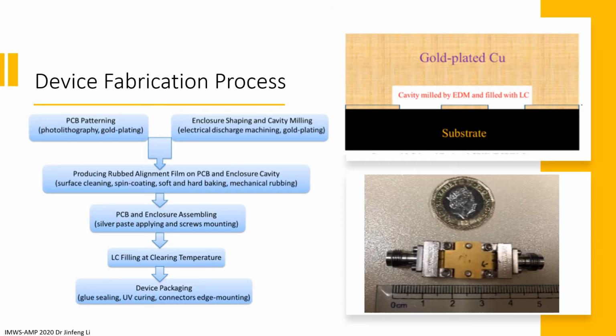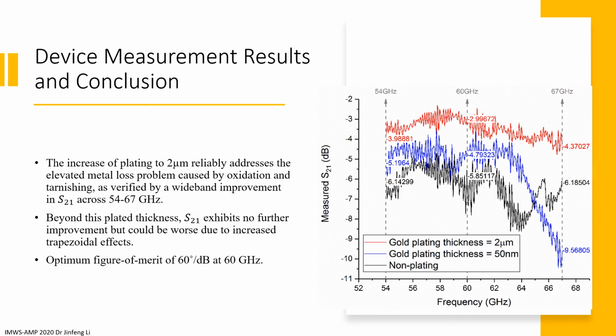Here we outline the device prototyping process. After lithography, the patterned copper-based substrates are given a surface finish with gold following a nickel-free electrolytic process. The thickness of the gold plating is experimentally investigated for reliable protection without degrading the conductor's performance, especially after the 200 degrees baking. Finally, we show the measurement results.